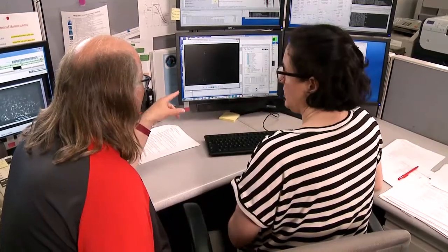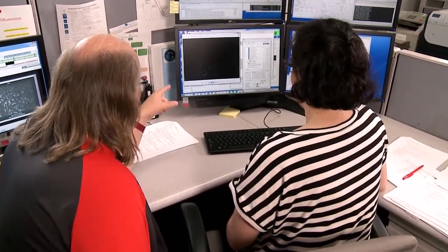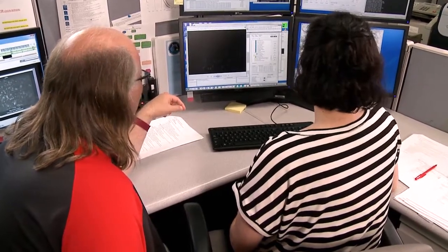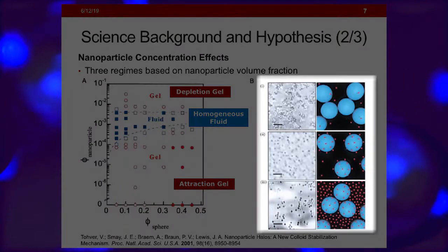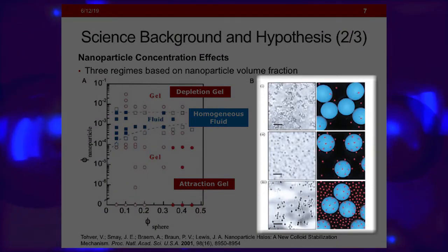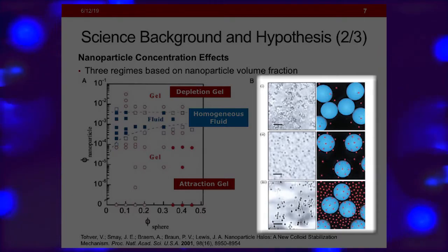ACT12, what we're doing is we're looking at how particles that are two different sizes, about 2 orders of magnitude different, with very different charges on them, will aggregate and hopefully crystallize in a microgravity environment. The nanoparticle haloing refers to the fact that we have small particles that are very highly charged that basically protect the large particles which are uncharged. And this allows our system to be much more stabilized and have long-term stability.